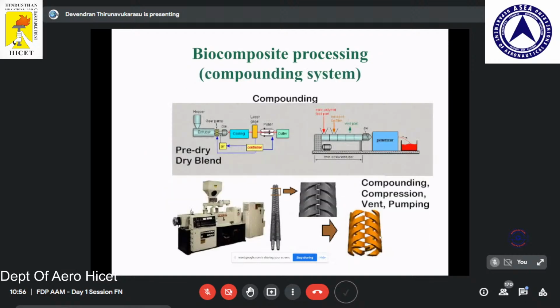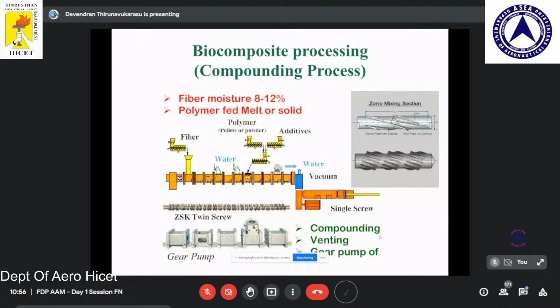So this is the process of pre-drying, blending and compounding of the natural fiber and high density polyethylene. The material is melted here, and we optimized the twin screw extruder blades, because we are using natural fiber. If it is a conventional screw extruder, it damages your fiber. That's why we optimized the twin screw extruder blades.